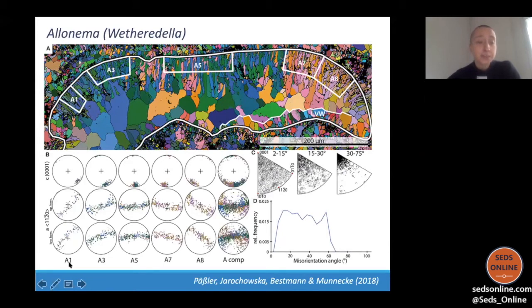Now, these pole figures refer to different areas of the specimen. And you can see the top row is when we look from the top of the C-axis. So we look C-axis down, and you can see that the C-axis is perpendicular to the surface of the shell, whereas the A-axis, we're looking at calcite this time. In the first slides, I was showing aragonite. This is calcite. Calcite crystallizes in a hexagonal system. It has only three A axes. It doesn't have a B axis.